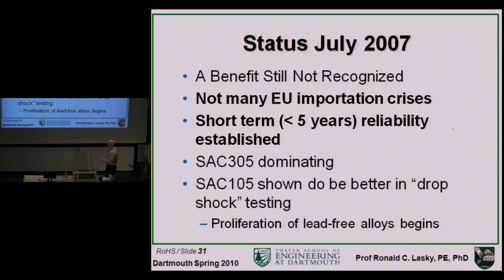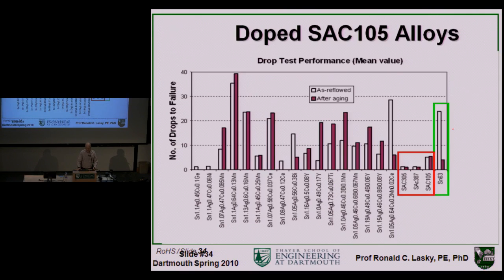And so this has started what I'll call the proliferation of lead-free alloys, because it looked like everybody was going to focus in on this. And yet when we found this out about SAC 105 being better in drop shock testing, we started investigating this more. And this is some work done by my colleague Ning-Cheng Lee at Indium Corporation. This was the number of drop cycles that tin lead solder would survive, the clear being after it's reflowed, and then the purple being after aging. And aging was pretty gentle, 150 C for 4 days.